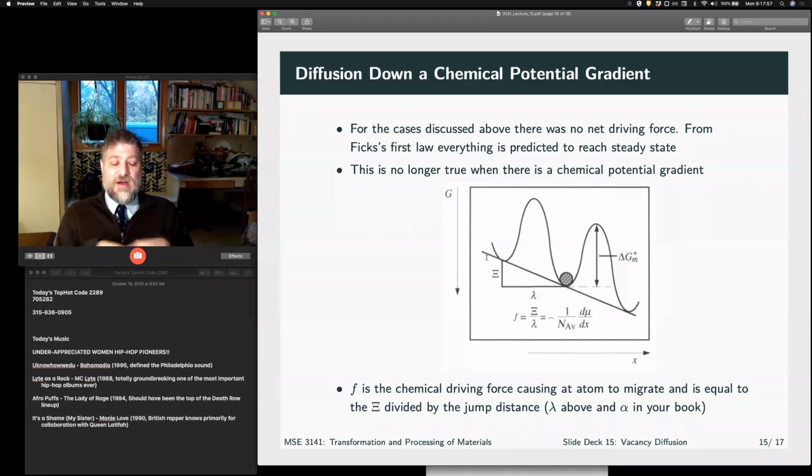And so eventually it equilibrates out, right? That effect is simply due to the fact that the jumps are random forward and backwards, and given enough time, if each solute atom acts as a completely random walk, they're going to be uniformly randomly distributed.